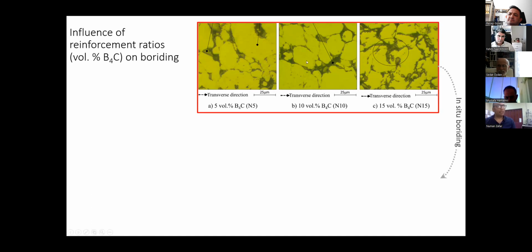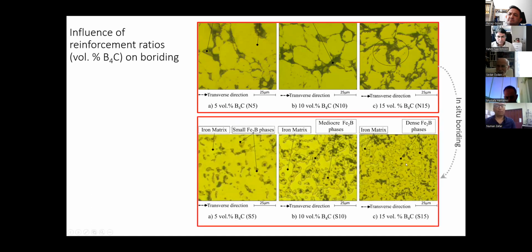So these are the particles before boriding. In situ boriding has caused the formation of iron borides in such a way. You can see that the lower reinforcement ratios have caused a smaller iron boride phase synthesis. These darker regions are iron borides and the background is iron matrix. These are also iron boride phases, and this is also dense iron boride phase.